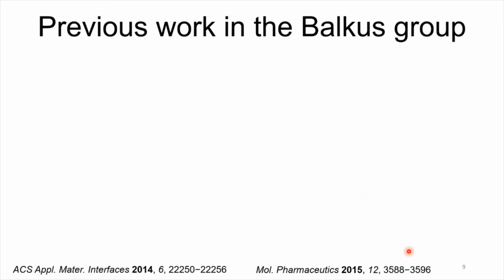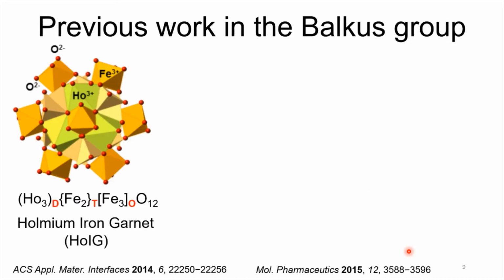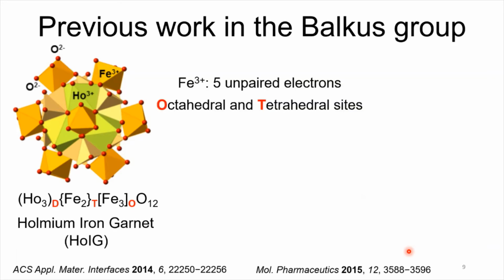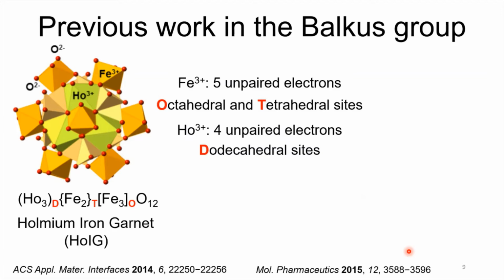Nevertheless, some previous work in the Balkus lab has shown very good results. In particular, I want to focus on this structure, holmium iron garnet. This structure is really interesting because we have holmium and iron sites here, and the iron is situated on the octahedral and tetrahedral sites. Each of these irons will have 5 unpaired electrons, while holmium sitting on the dodecahedral sites will have 4 unpaired electrons.